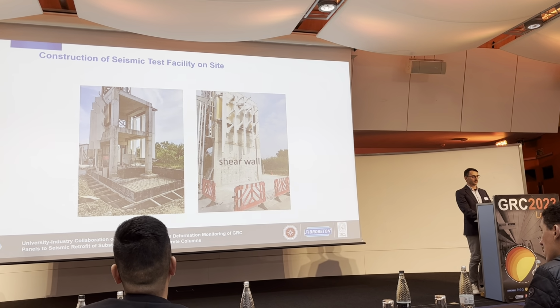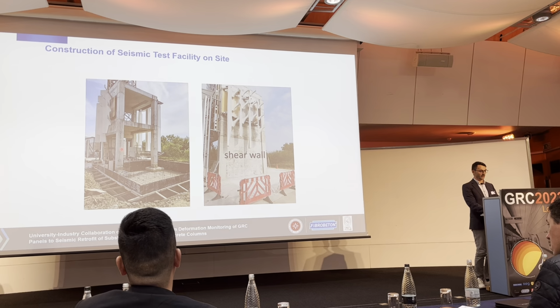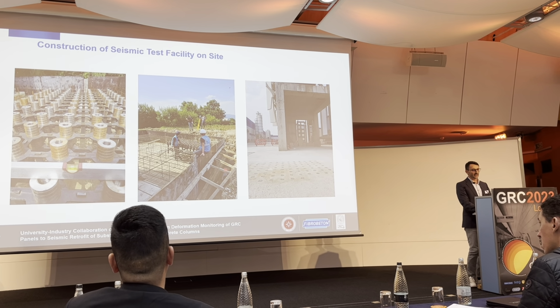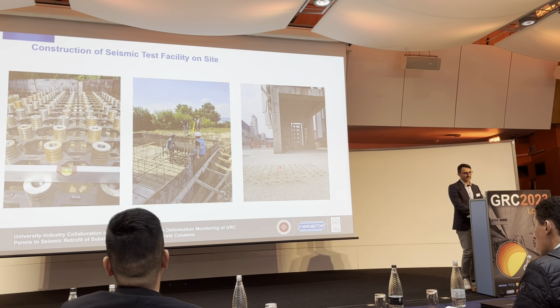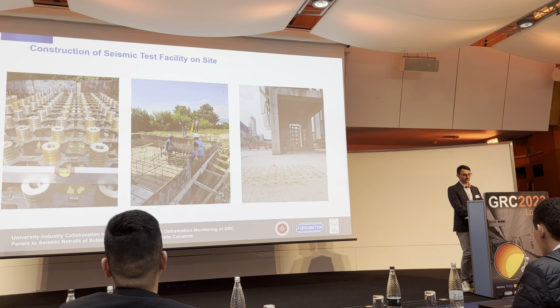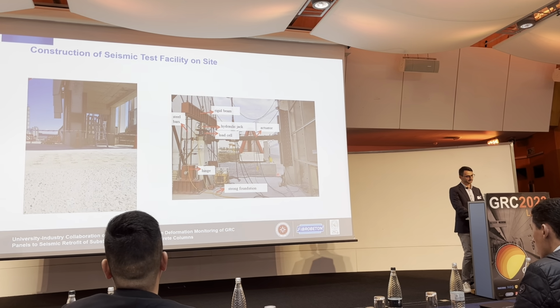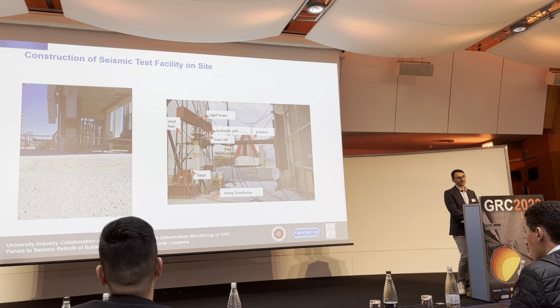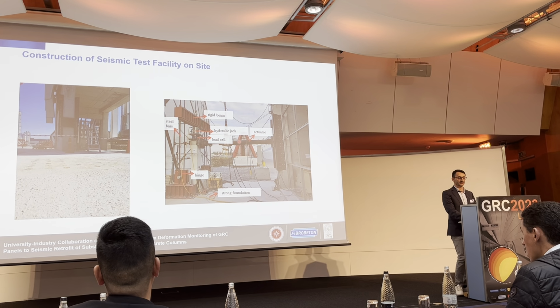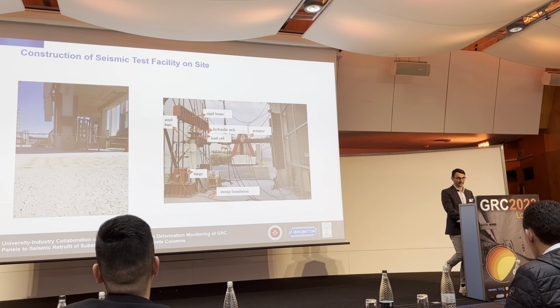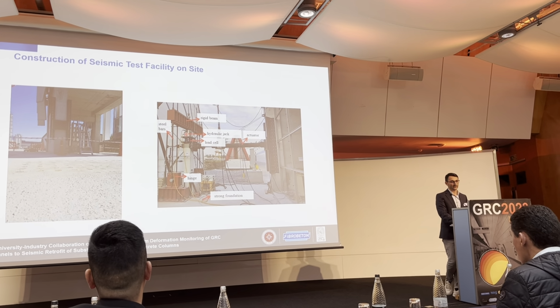We added some shear walls in order to create a strong reaction wall for such seismic tests. Then we created a strong floor in order to apply some axial loads at the floor level, as you can see. And that is the final case. We have constructed some full-scale reinforced concrete columns, representing the existing building stock. Using this horizontal actuator, which is capable of applying around 60 tons of horizontal load, and some jacks capable of applying 200 tons, that was the capacity needed for some columns with high aspect ratio.